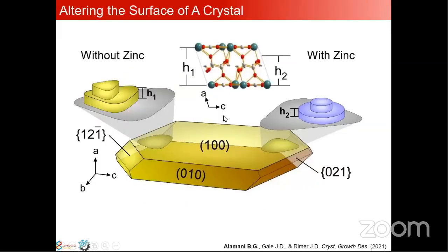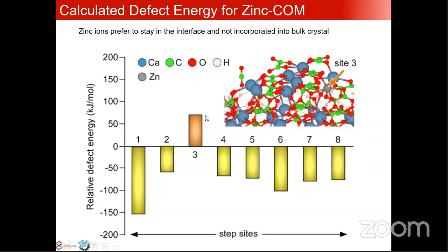And lastly, ultimately, what you've seen here is that the presence of zinc can actually alter the surface termination. It can lead to potential changes on the shape of the growing crystal, or possibly the growing layers that will ultimately result in your final crystal. To corroborate our study, we partnered with Julian from Curtin, and he mentioned to us that zinc actually prefers to stay on the interface, and that can definitely influence the overall crystallization process, because crystallization itself is inherently